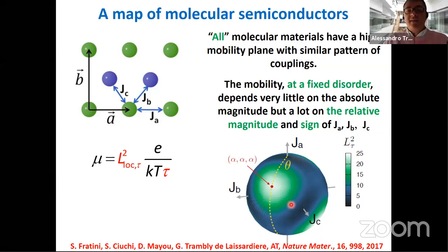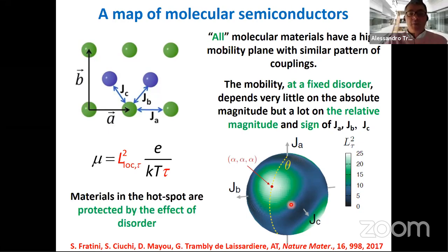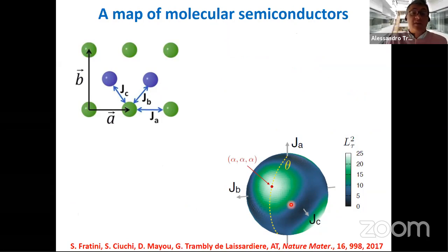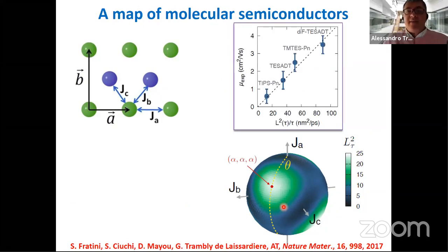However, when we submitted this to the journal, they said, well, why don't you show some experiment on top? Because, of course, as per tradition, we believe experiment ruins the theory. And so we had to go back and search for experiments where intrinsic mobility was proven. And essentially what we found is that this model has a predictive ability that was beyond what we expected. If we consider a set of 4 materials which have been made by the same person in the same lab, we realize that the model predicts the correct order and scale of the mobility between them.